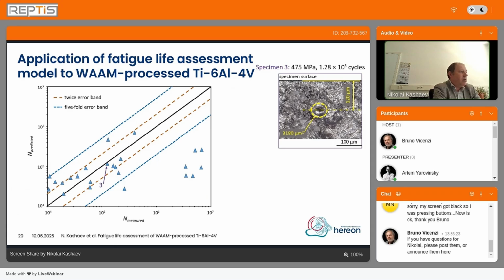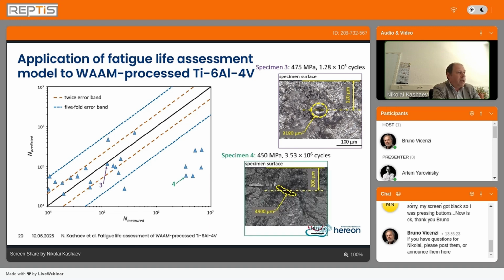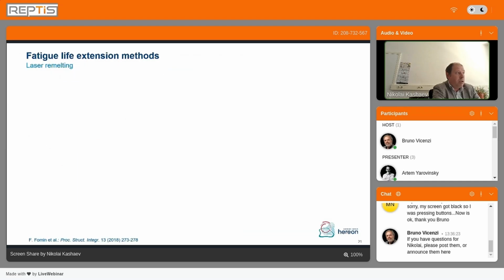But what could be the reason? If we have a good agreement, we have defects with a round or more elliptical shape. But if we have defects with irregular shape, the deviation is probably due to the question of how to consider the critical position of the defects with regard to the distance from the surface. And here we need somehow to further optimize our model. And that kind of approaches will now be investigated also within the REPTiS project for additively manufactured components.